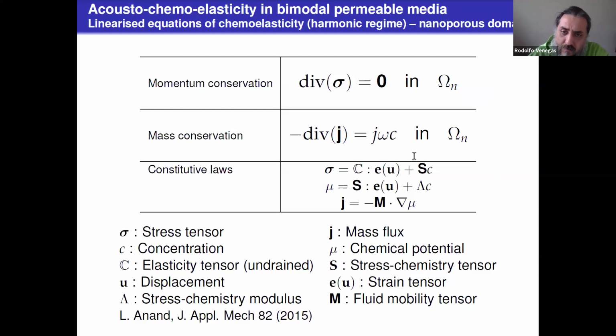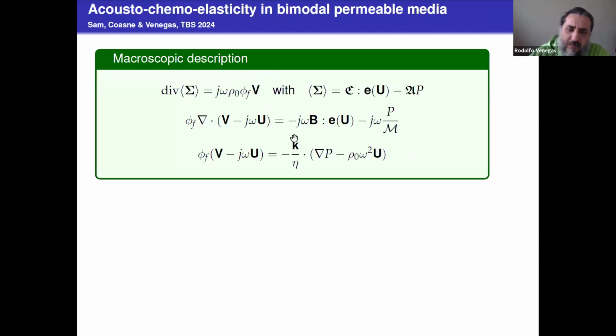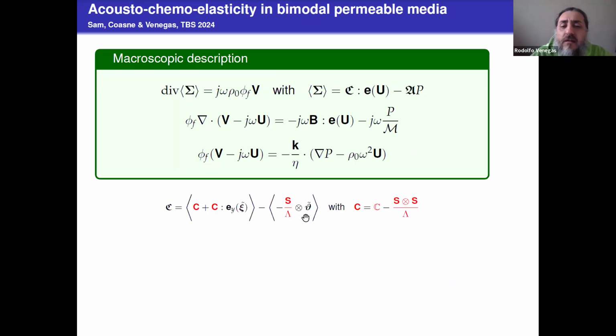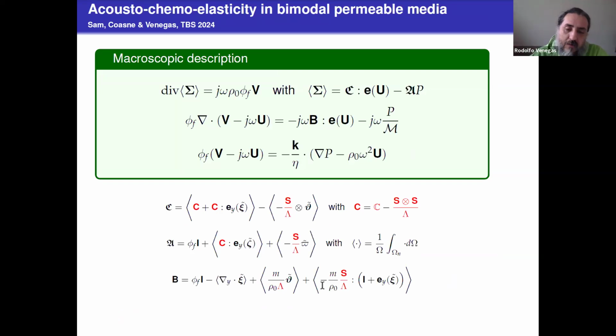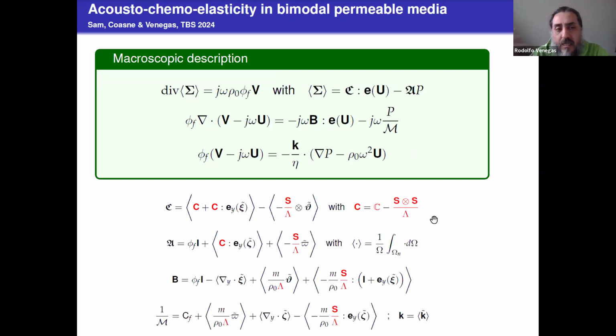And when we do that and apply homogenization, we get this macroscopic description that looks like the Biot model. But the difference is that these parameters are exclusive to nanoporous media, and all of these parameters in red can be calculated from molecular simulations. And we've done that, and we are in the process of finishing off this work. So we'll hopefully be able to discuss in more detail all of these results in no time.